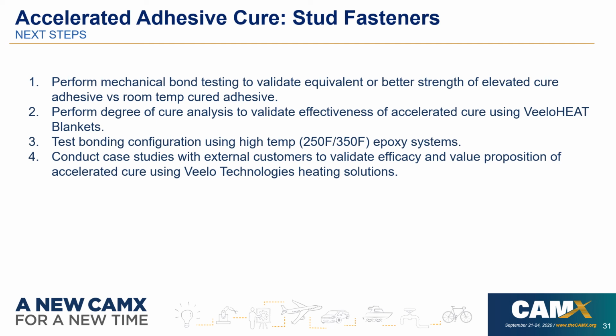So the results shown in this tutorial showcase the efficacy of accelerated cure using these small custom heater blankets. Really though, this is just proof of concept testing. Next steps are more of a systematic approach for testing these and validating that they work. First, perform actual mechanical bond testing to validate that we are achieving equivalent or better bond strength using the elevated temperature cure versus the room temp cure adhesive. Specifically, we want to dig deeper on the epoxy systems, and we'd like to perform an actual degree of cure analysis to validate the effectiveness of this accelerated cure using the blankets.